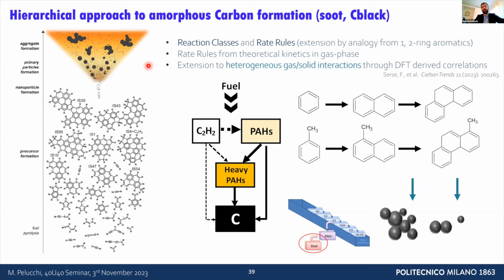So let's start gradually, from the gas phase. Everybody working on soot is familiar with this plot. The only difference is there's no oxygen in this case. So we start from cracking the fuel, we form the first ring aromatic, we form the precursor, then we get nanoparticle formation, then primary particle formation, and aggregation. So we go from the fuel to carbon in principle.